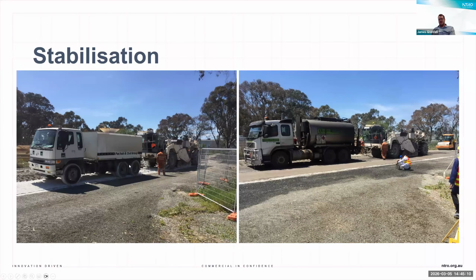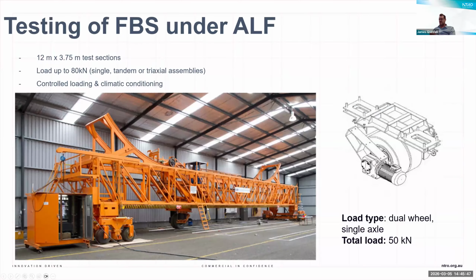So as I said, typically we're adding in hydrated lime in one pass. We have a stabilizing machine or pulverizer to blend the materials together. Second pass with the bitumen, so the bitumen connects up to the pulverizer. The bitumen is foamed in the foaming rig, or water's passed through. That's then mixed in the mixing chamber. The materials are then compacted with the heavy roller to form our foam bitumen stabilized pavement, and then we would seal with either a sprayed seal or a thin asphalt surfacing.